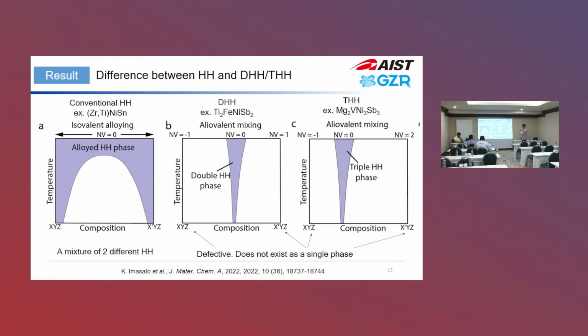And from the definition, I would like to mention the terminology difference between just a disordered alloy Half-Heusler and double or triple Half-Heuslers. Conventional Half-Heusler also makes alloying on one side, so it looks like a double Half-Heusler composition, but it's actually different. If you look at the phase diagram, both end members are stable, and if you go to higher temperature, it's just mixed as an alloyed Half-Heusler phase. But actually, at 0 Kelvin, it should be a phase separation or something, right? On the other hand, with double or triple Half-Heuslers, the end members are not stable as a single phase, so there is probably no single phase region.